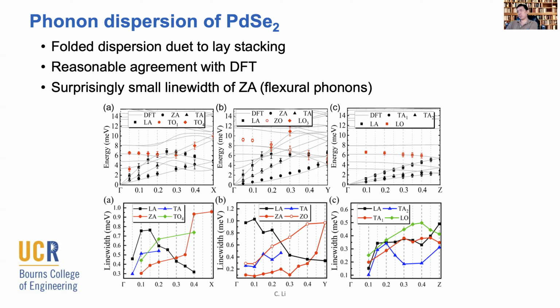And you can see that it actually agrees reasonably well. In particular, if you look along gamma X, which panel A shows, and gamma Z, which panel C shows, most of the phonon branches agree pretty well with a harmonic calculation. And the model actually works pretty well. Even the van der Waals interactions seem to be predicted well when we are using one of the potentials, which includes a van der Waals component used to describe these van der Waals interactions.